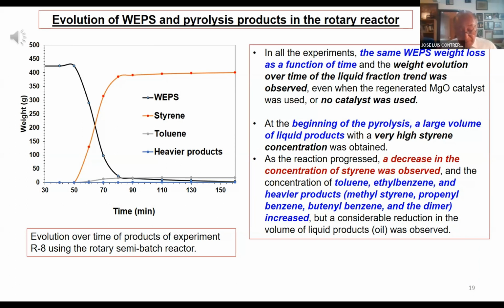At the beginning of the pyrolysis in the rotary reactor, a large volume of liquid products with a very high styrene concentration was obtained. As the reaction progressed, a decrease in the concentration of styrene was observed, and the concentration of toluene, ethylbenzene, and heavier products increased, but a considerable reduction in the volume of liquid products was observed. In all the experiments, the same weight loss as a function of time and the same weight evolution over time of the liquid fraction trend was observed, even when the regenerated magnesium oxide catalyst or no catalyst was used.